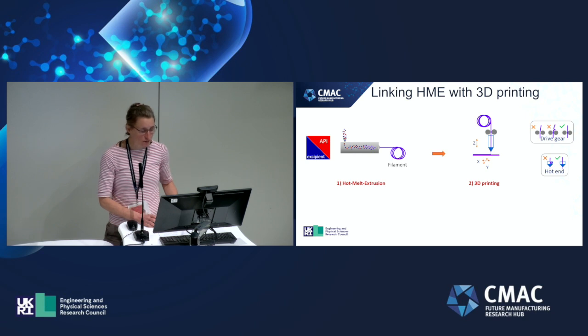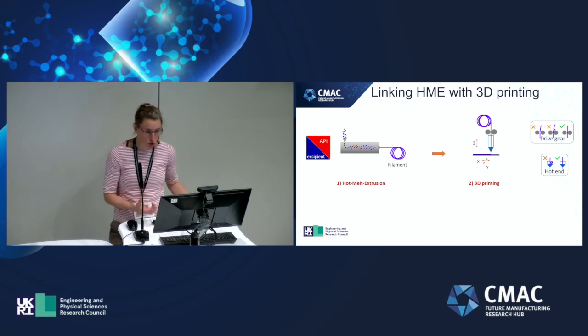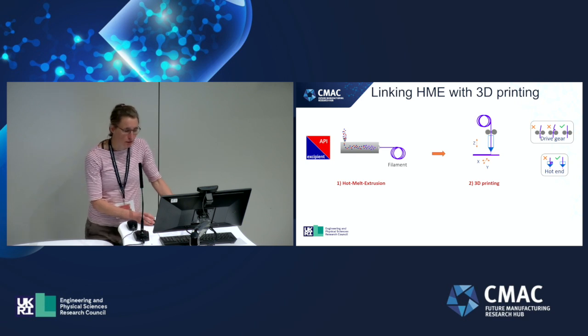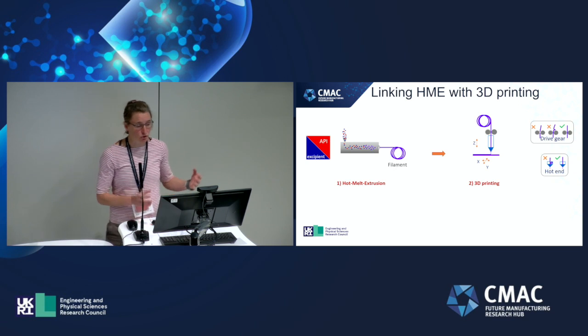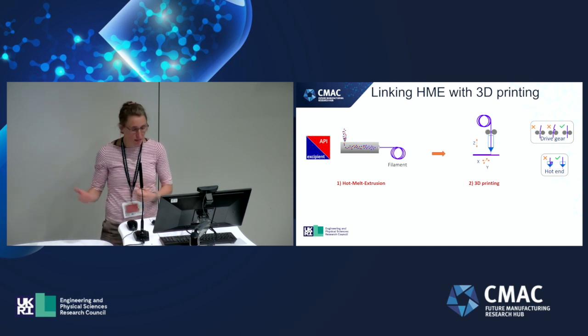Now, this process is very dependent on the properties of the filament, the material properties, the formulation properties. There are certain failure modes associated with this, either the material being very brittle and breaking in the drive gear, or at the other extreme, the ductile failure of the material. So it's just too soft, it doesn't have enough structure to be fed by a drive gear, or it buckles in the hot end.